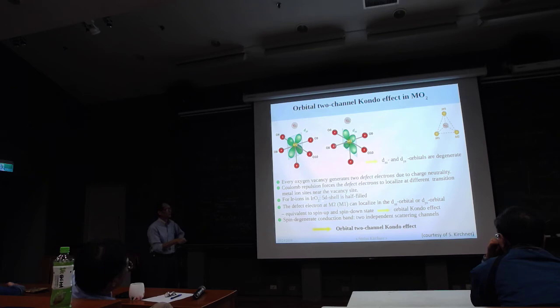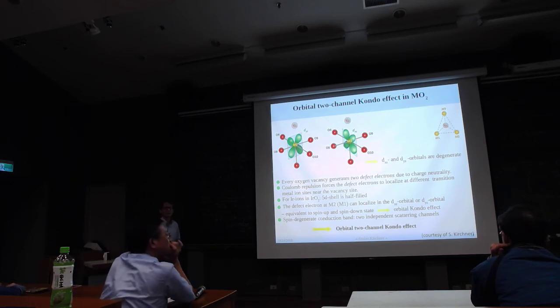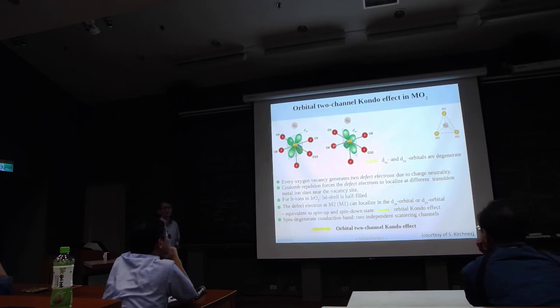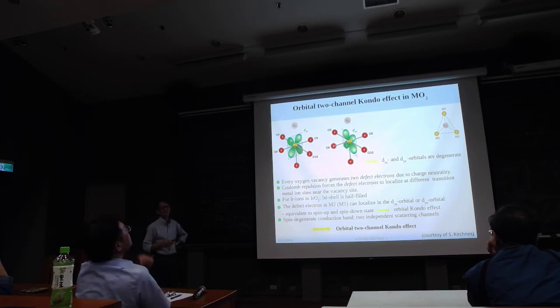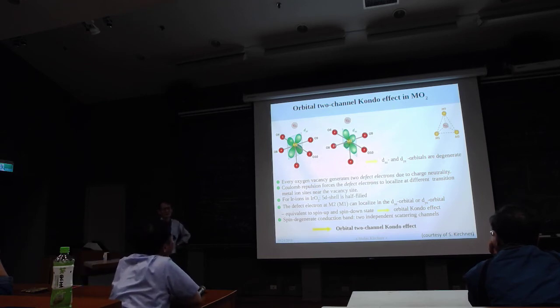In this crystal structure, originally, if you have no oxygen vacancy, the iridium atom is in the d shell up here. And now you have one electron. We call it the defect electron. This is your quantum defect. And this defect has two positions, two orbitals to go to, dyz or dxz. So that defect, the scattering center, gives us this orbital Kondo effect.